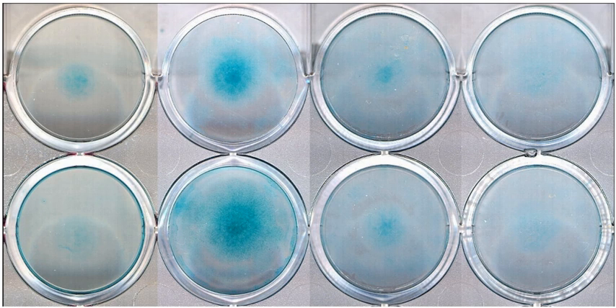The size of the porogen particles will affect the size of the scaffold pores, while the polymer-to-porogen ratio is directly correlated to the amount of porosity of the final structure. After the polymer solution has been cast, the solvent is allowed to fully evaporate, then the composite structure in the mold is immersed in a bath of a liquid suitable for dissolving the porogen, water in the case of sodium chloride, saccharose and gelatin, or an aliphatic solvent like hexane for use with paraffin. Once the porogen has been fully dissolved, a porous structure is obtained. Other than the small thickness range that can be obtained, another drawback of SCPL lies in its use of organic solvents, which must be fully removed to avoid any possible damage to the cells seated on the scaffold.